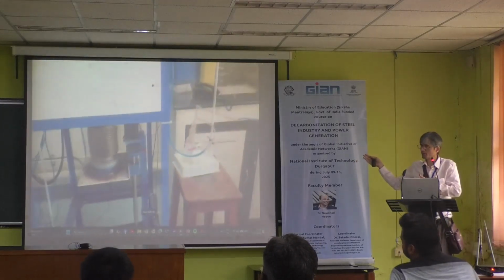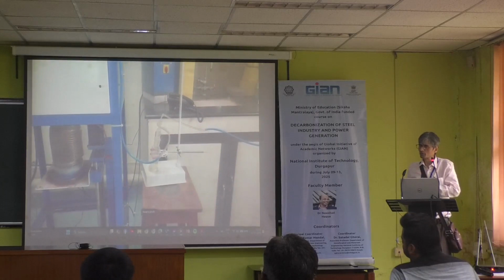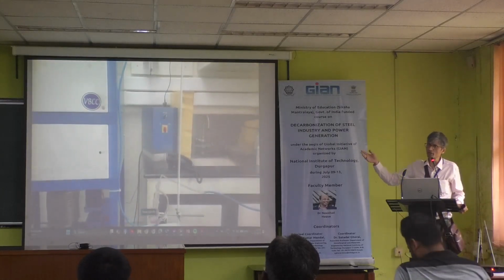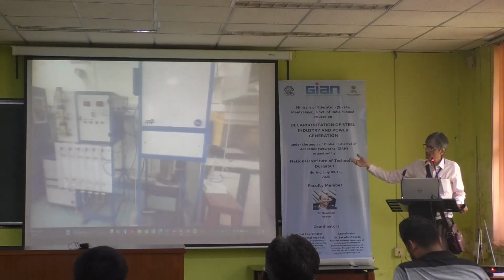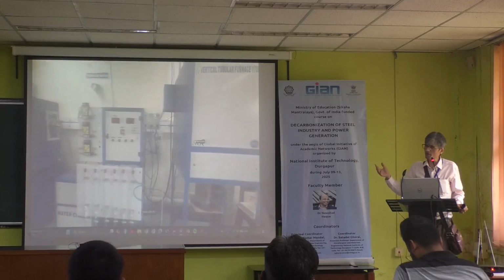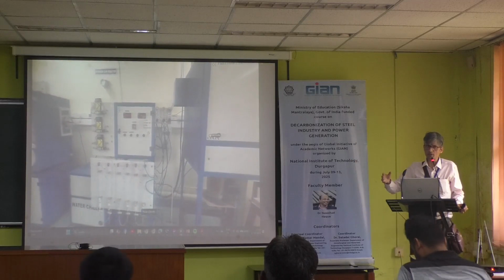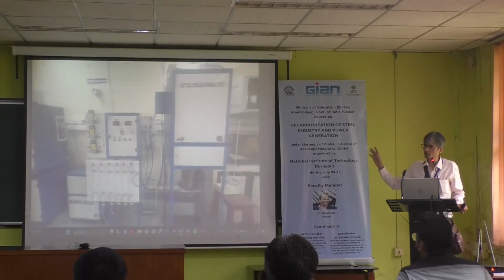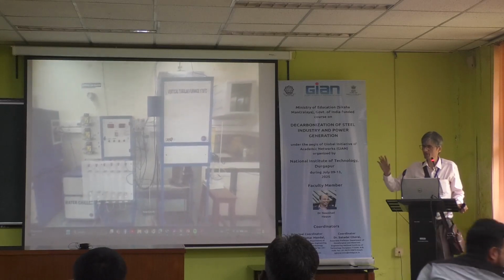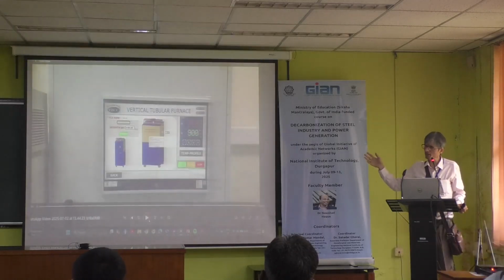For example, earlier my student did the experiment for Indian iron ore, and we were able to find out the utilization ratio of hydrogen for Indian iron ore. It is a function of iron content. If it is a better iron ore, then obviously that ratio will be lower; if it is a lean iron ore, it will be more. Accordingly we used those parameters to decide the duration of the experiment, and we did the experiments and are getting results to investigate further.